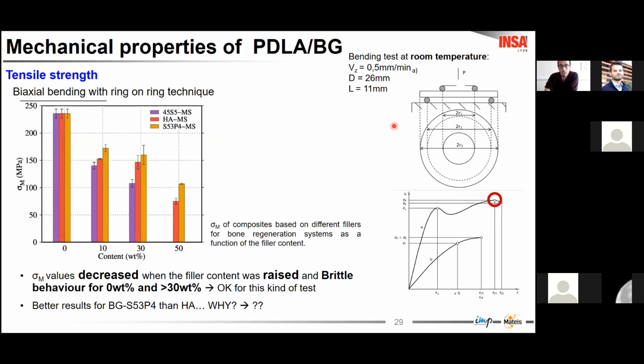For the geometry obtained in the study and the low elongation at break, we decided to do a biaxial bending test to obtain the ultimate tensile strength and the modulus of this kind of biocomposite.